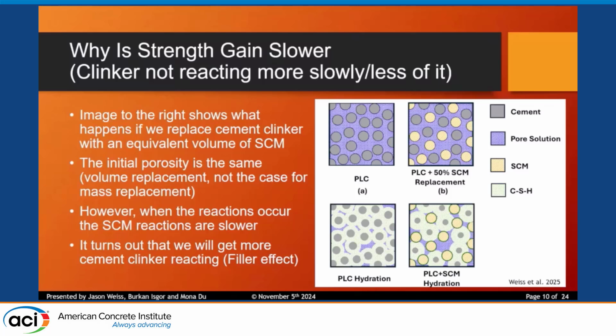So if we do a volume replacement, which we are not currently doing as an industry, but should, because most of these materials have a different density than cement, we have the same initial porosity, right? The material is going to flow in a very similar way. The other thing, though, is if these things start reacting, you can think about how these materials react and how they stiffen as sort of these cement particles growing some kind of a Velcro on their surfaces. And when that Velcro starts to interact with each other, that's all of a sudden when the rates of reaction start to slow down. When we replace a lot of that clinker with something else, we have more room for the Velcro to grow, right? So we actually get more reaction out of our clinker, and this is commonly referred to as the filler effect.